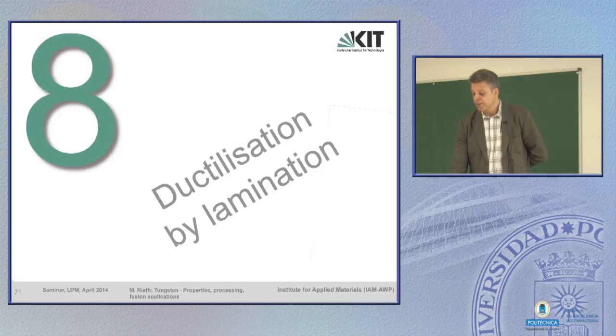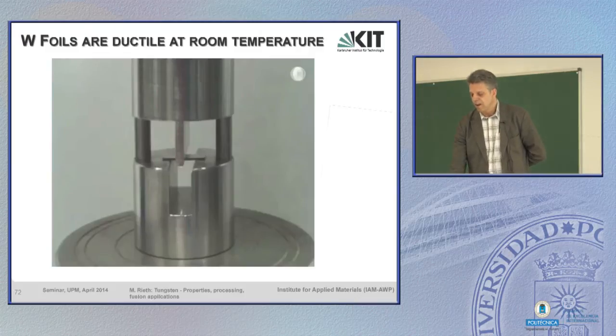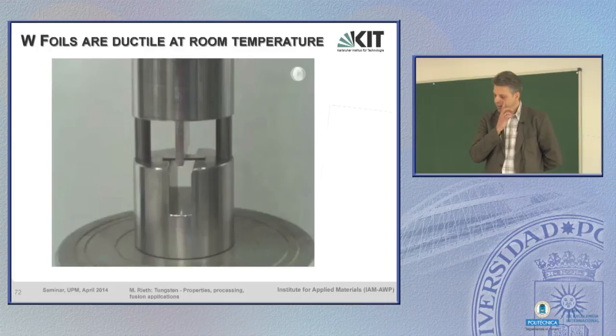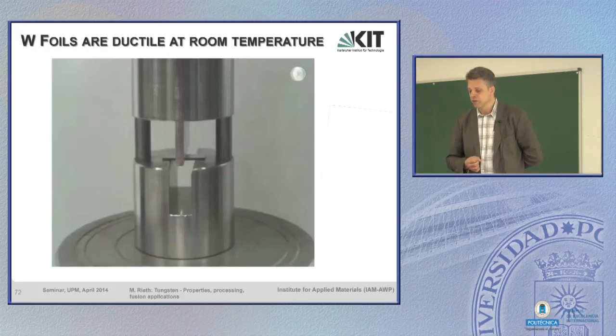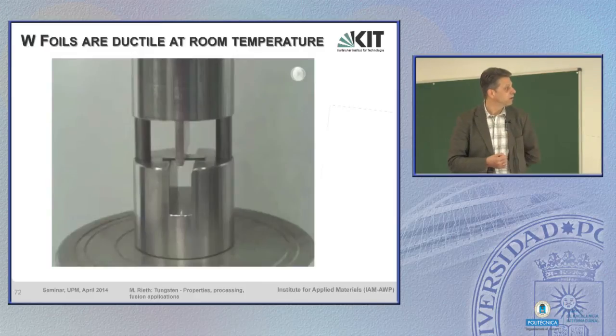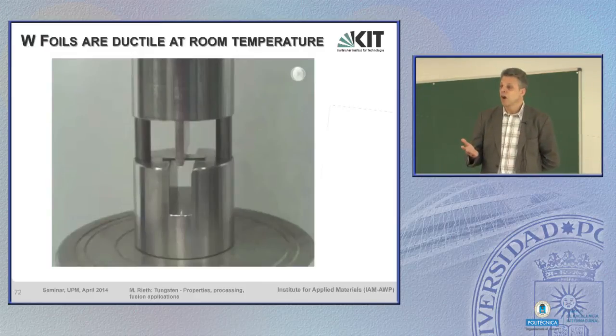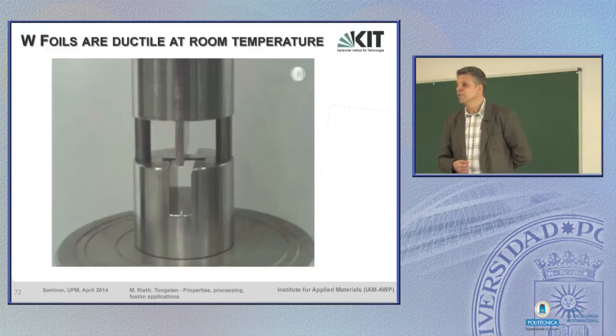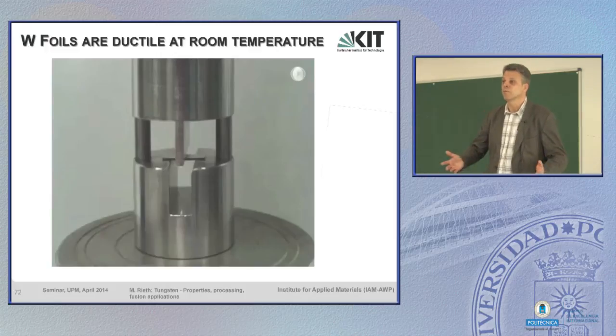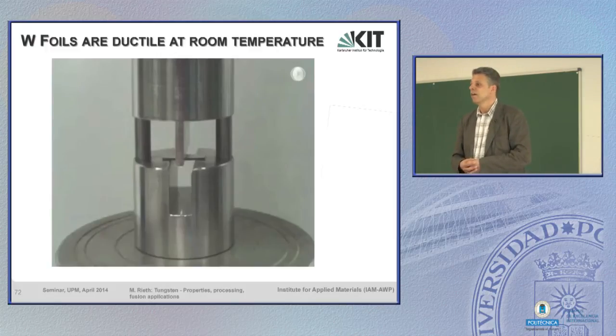And this leads finally to another way to produce ductile tungsten materials. If you see this test, this is a stack of tungsten foils at room temperature, and you can bend it very easily without any fracturing. It even behaves ductile. So, well, why do we not use tungsten foils? Of course, you cannot build up a whole power plant from tungsten foils.